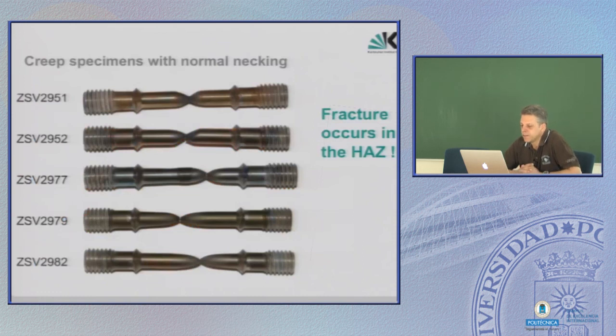This is how the specimen looked after breaking in the creep test, and the only interesting and important thing here is, and you can see it best in this specimen, this here is the electron beam or laser beam weld, this small area. And this keeps completely its diameter, and the necking appeared a bit on the left side and on the right side. And this is a general observation for all these creep tests and all these welded specimens.